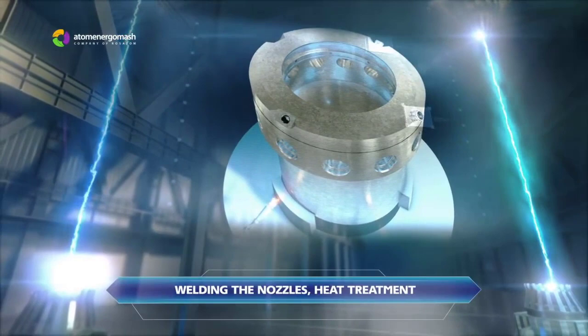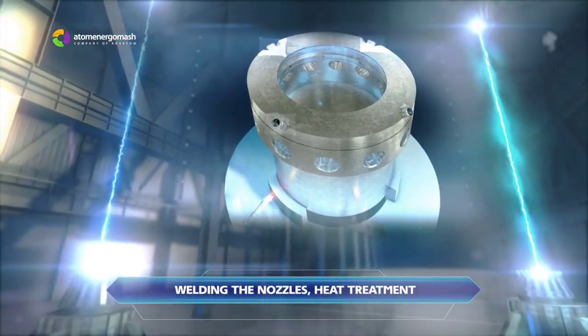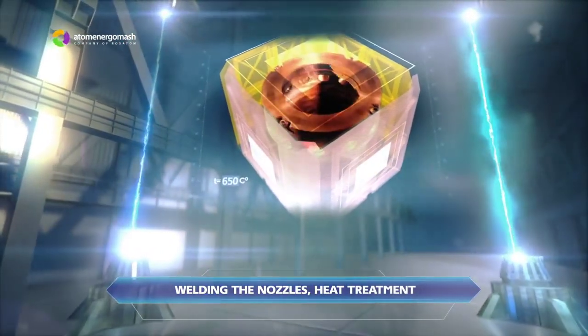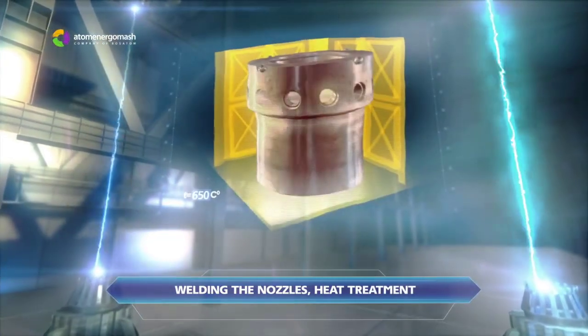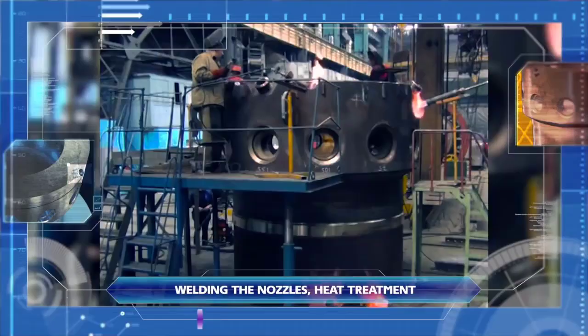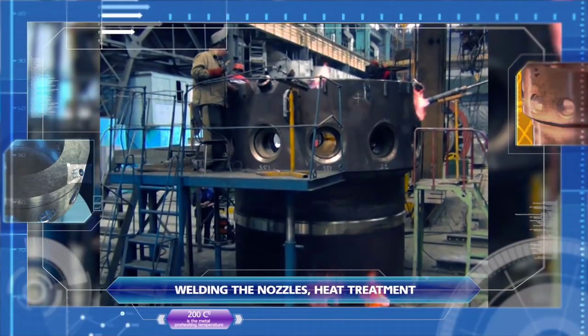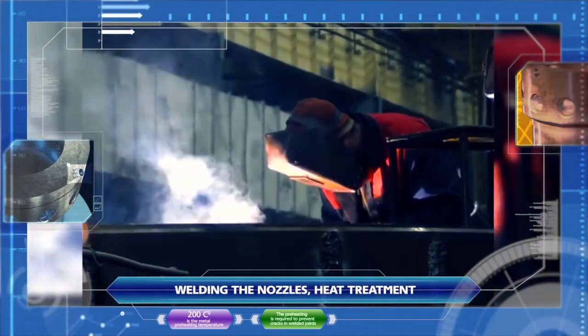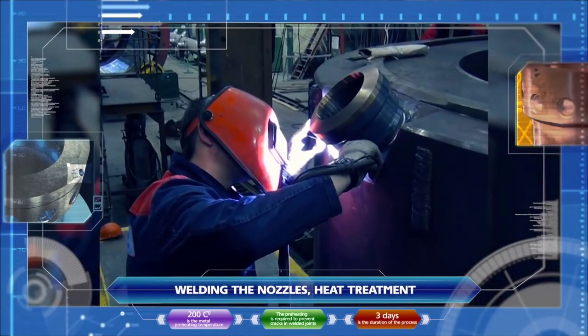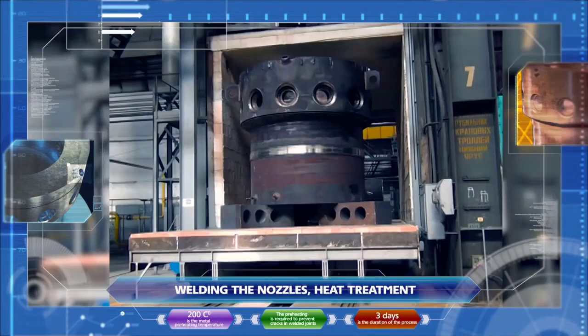Step 5. Welding the nozzles. Heat treatment. The reactor nozzles will continue to be welded. The metal block is heated at a temperature of 200 degrees Celsius. Preheating is necessary to prevent cracks in the weld. This process takes 3 days.